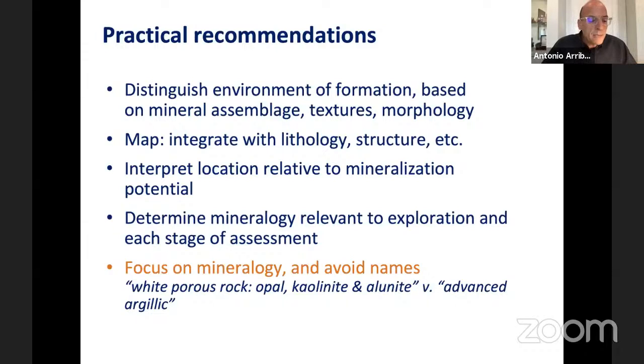I don't trust so much some of the claims by people in the spectral community business that you can distinguish high temperature alunite from low temperature alunite, or high temperature illite from low temperature illite. I don't think the tools are always reliable enough to say that only with that tool. So kaolinite from halloysite, frankly, I don't know if you can distinguish with infrared spectroscopy. I doubt it.